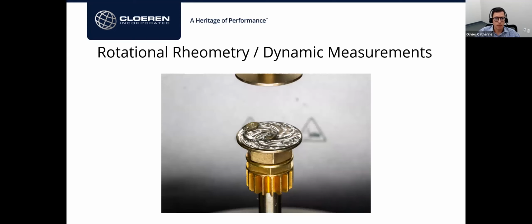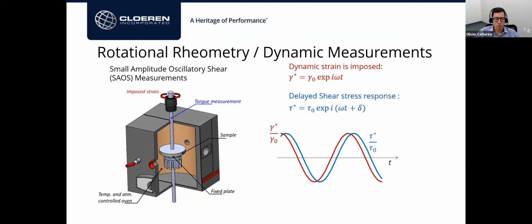So another technique that we, for example, use in our lab here is rotational and dynamic measurements. And the main reason is that this technique can bring a wealth of information regarding the viscoelastic behavior of the material. There are different ways to perform measurements, but here I'm showing a typical setup where we use either a cone and plate or a parallel plate geometry, and we use the equipment in small amplitude oscillatory shear experiments. So basically we are shearing the material at a frequency, and we're going to vary that frequency.